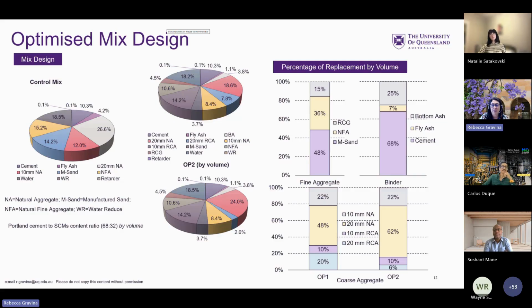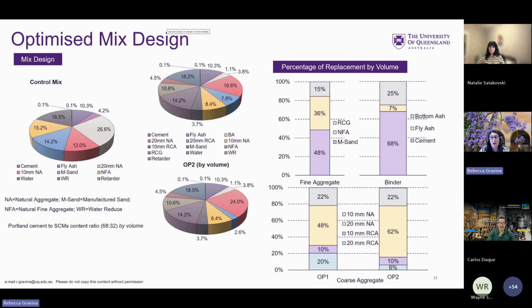In terms of the fine aggregate, we have about 64% replacement of natural sand with recycled crushed glass and man sand. In terms of the cement, as I said already, a 68 to 32% by volume comparison. And of the SCM content, the majority, 75%, is bottom ash. The other 25% is fly ash. So we've nearly got full fly ash replacement. And in terms of the coarse aggregates, we are using a 30% coarse aggregate replacement with recycled concrete aggregate.